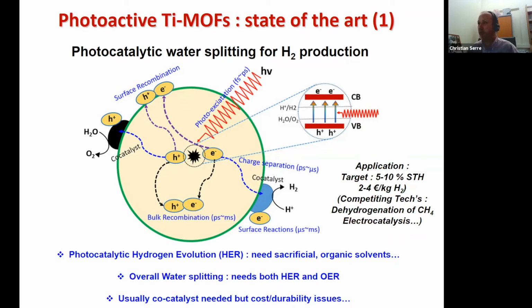And then the idea is to combine often with a co-catalyst that will accept either the positive charge or the electron in order to produce hydrogen or oxygen. And then the targets, especially for hydrogen, are quite tough. You want to have 5 to 10% solar efficiency, and you want very low cost for hydrogen. And you need to compete with techniques that are maybe not good for the planet, but that work better and are cheaper, like the dehydrogenation of methane, or alternatively, electrocatalysis that works very well in terms of yield, but then requires a lot of energy compared to what is gained from the production of hydrogen.